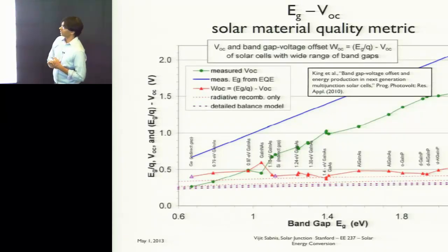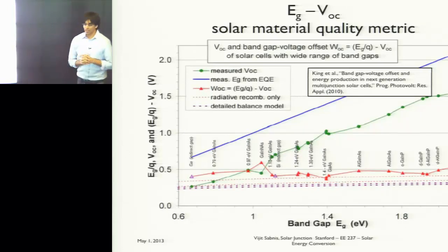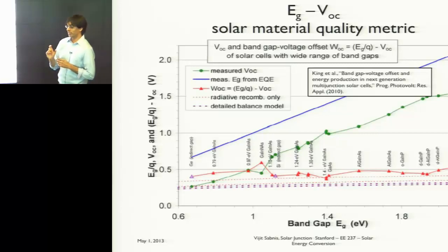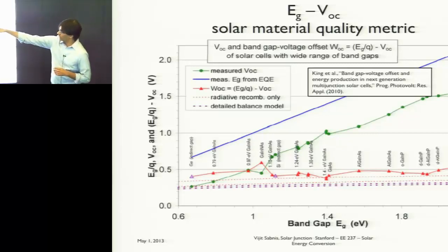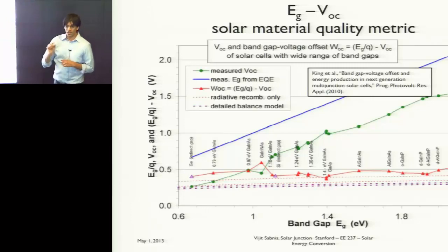This was a plot published by Richard King at Spectrolab back in 2010, and he's a big proponent of using your band gap minus your open circuit voltage as a metric for how good your material is. What he plotted was, if you look at the blue curve, your measured band gap versus different materials. And then in green, your measured VOC versus your different band gaps, your different materials. What you'll find is the best materials have an Eg minus VOC of about 400 millivolts.